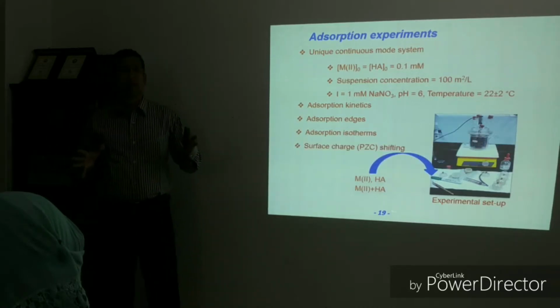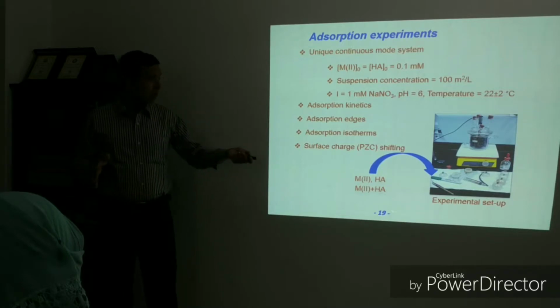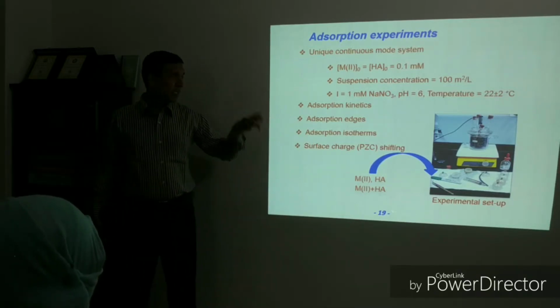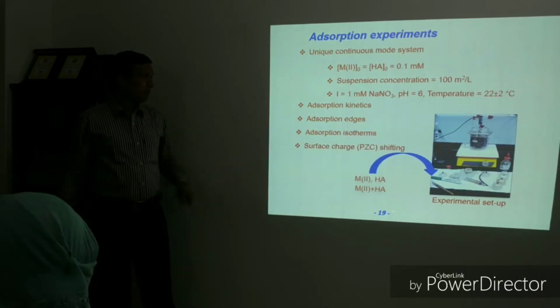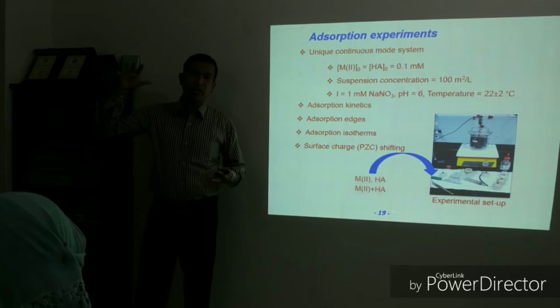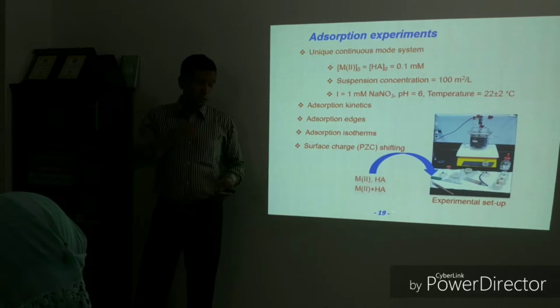Then we have performed adsorption experiments. This is a very unique experimental system, which is known as the continuous mode experiment system, in which the suspension was in the reaction vessel. Here we have shown the reaction vessel for the entire period of experiments, and these are the experimental conditions. We have studied adsorption kinetics, adsorption edges, adsorption isotherms, and surface charge shifting to understand what actually happens when various pollutants adsorb onto the surface.